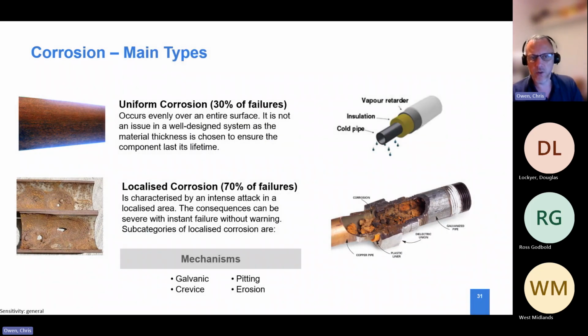And again, when we look at the types of corrosion failures, uniform corrosion is only about 30%. Localized corrosion is really where the main issues occur. When we talk about uniform corrosion, normally within a pipework system you'd expect to see some form of uniform corrosion take place initially. But once the oxygen is depleted, that system stabilizes and then it will just sit there nicely.